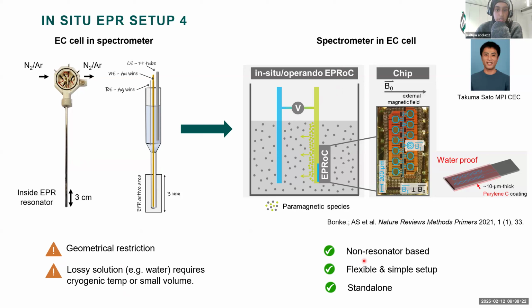Whereas in spectroelectrochemistry, with this EPROC, here you can see an image of the actual sensor, so the chip. You can just place this inside an electrochemical setup, and the coating that it has prevents it from degrading, one, and then also any interference coming from lossy samples. So it's non-resonator based. Once prepared, it's quite flexible and simple to use, and it's standalone.